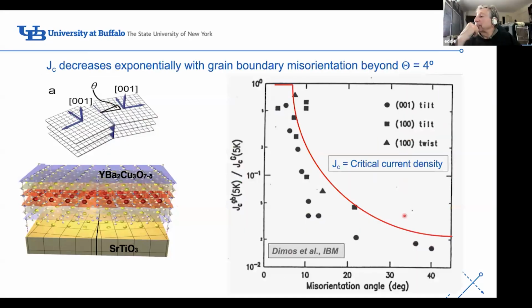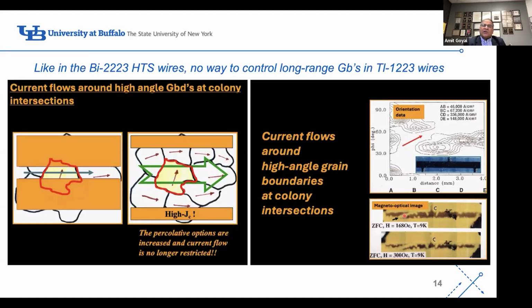Right. Can I just ask how wide is the grain boundary? So these grains here are a few microns. Each individual grain would be a few microns. But the boundary itself? The boundary itself, you can approximate it as, in these thallium-1223 wires, of course there is a range of grain boundaries in these materials. Let's say 2 to 10 microns, and you can envision it as approximate it as a circular grain of about 2 to 10 microns. And so, approximately that would be the grain boundary.